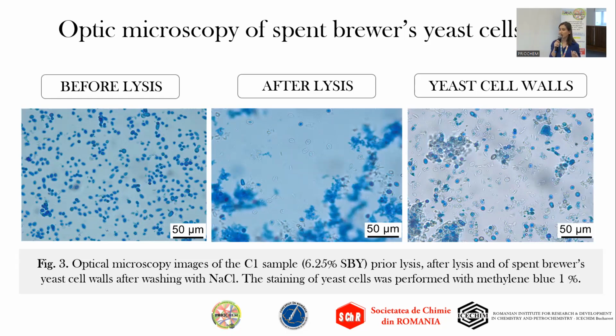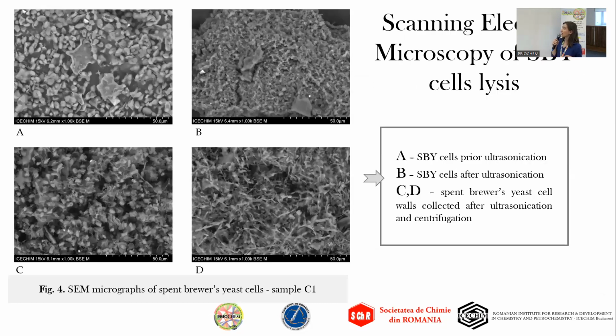In the third picture, it can be observed the yeast cell walls collected after centrifugation, after the supernatant was discarded. Yeast cell walls appear as almost round-shaped white circles. There are, of course, also some intact cells still. Scanning electron microscopy was also used to observe lysis efficiency. We assessed the same optimal sample prior and after lysis. Prior to lysis, the cells can be observed to be morphologically normal and intact, and the third and the fourth picture show the obvious breakages in cell membrane, and the disrupted yeast cell walls can be observed. So basically, scanning electron microscopy confirms that lysis occurred and it was efficient.